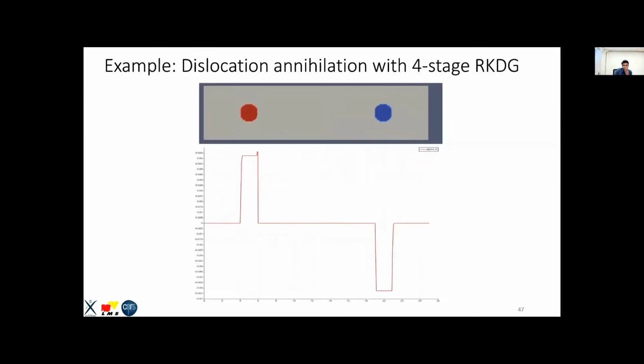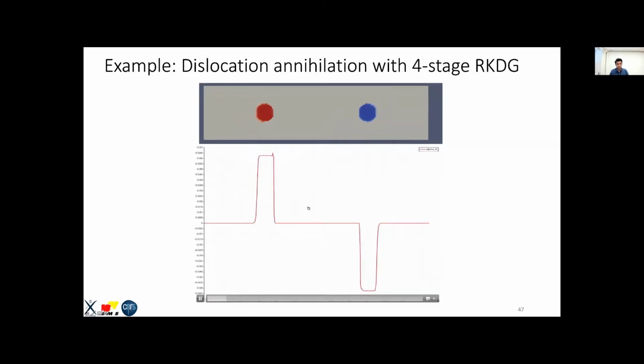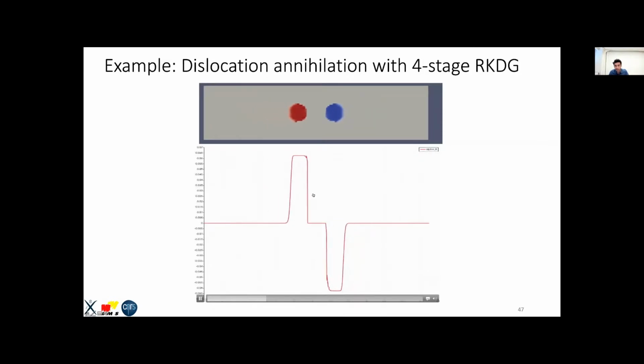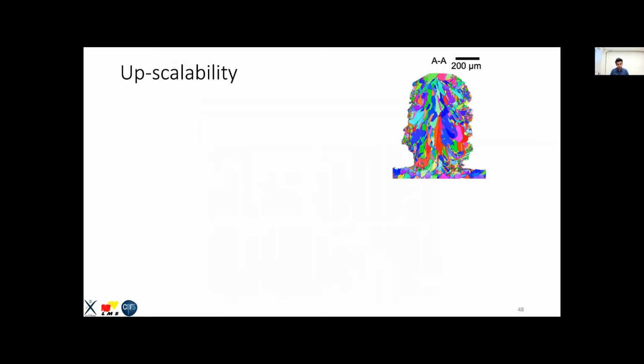And here is the simulation. Now, I think you can see it. What you see is that it started with this width and it maintains this width all the way. That means there is no spurious diffusion of the solution. And here you see these two dislocations are annihilating. And at the end, we get a residual of 10^-12, with a relative error of 10^-10. So it's a very, very stable and good final solution.